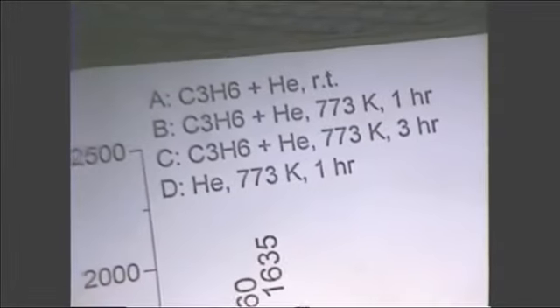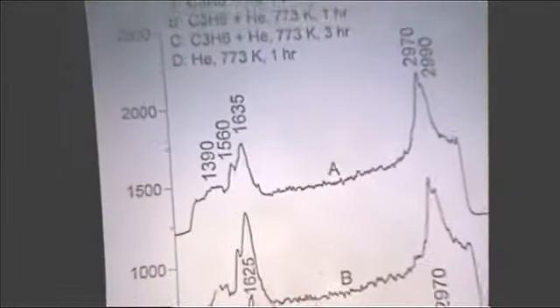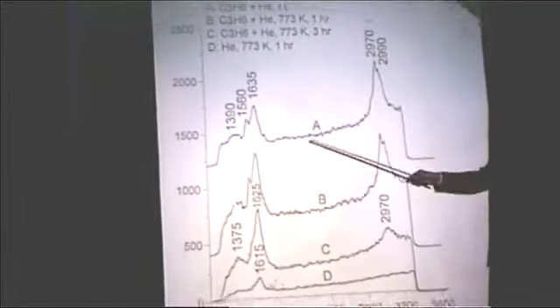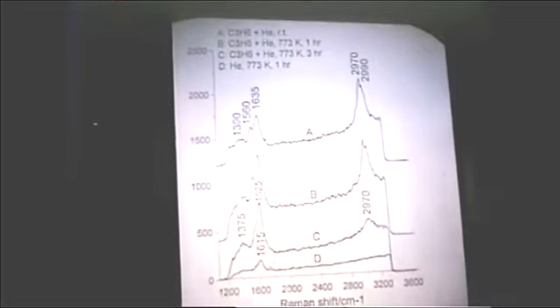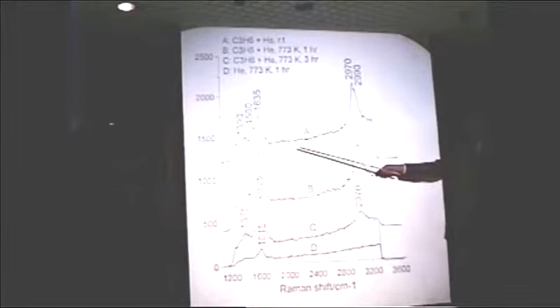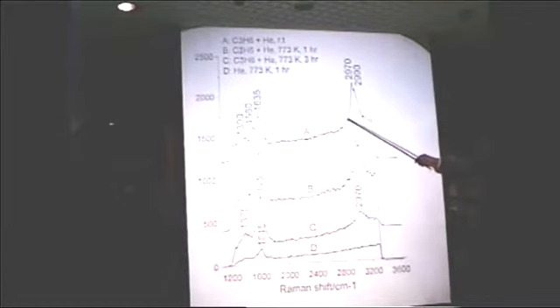So the first spectrum here, how do we do this? Well, we just expose the sample at room temperature to propylene and helium, then we purge with helium, and then we take a look at it. And this is what we see. So this is not propylene anymore. Already at room temperature on this catalyst, the propylene has formed a layer which doesn't come off in helium. And if you look at the positions of these bands, both the CH region and the CC stretch region, this is characteristic of what one might expect for a polyolefin on the surface.